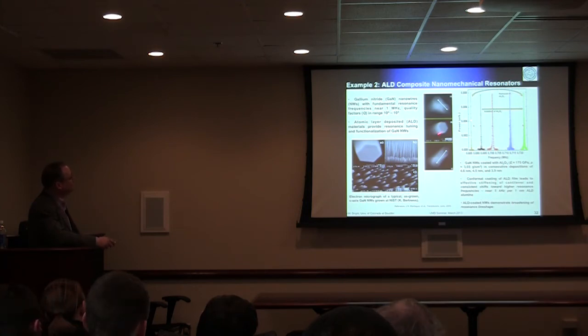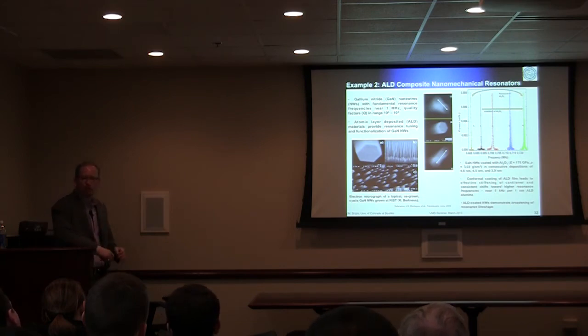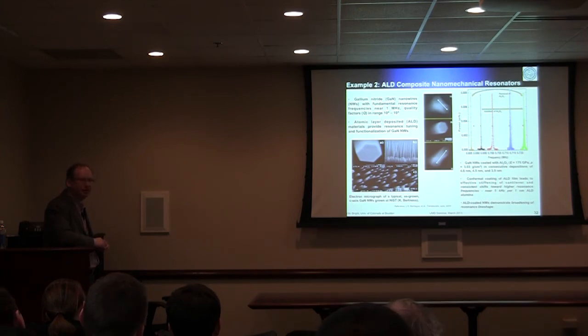The other thing that it actually shows is this makes a very sensitive thickness monitor. So you can put this in the ALD chamber, and you can measure how much ALD film you deposit. It sort of replaces your quartz crystal microbalance with a nanowire sensor.